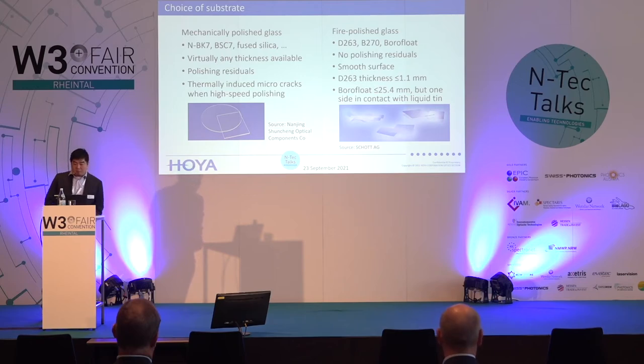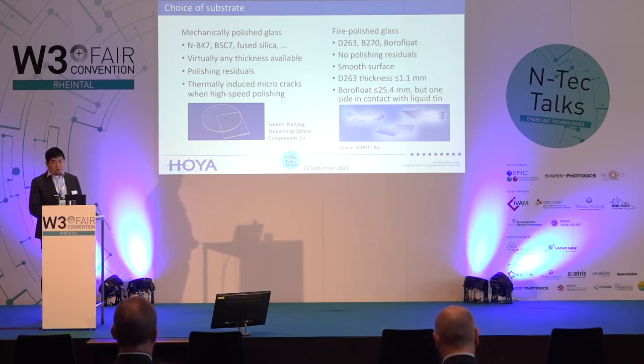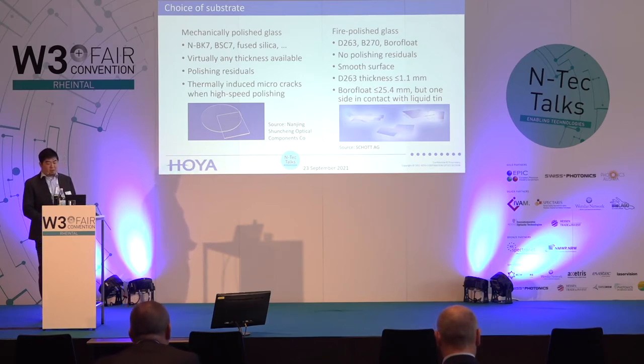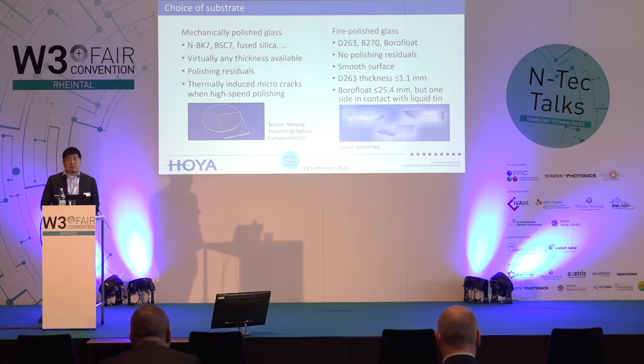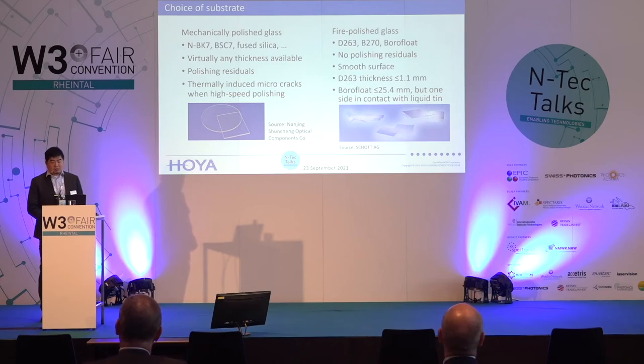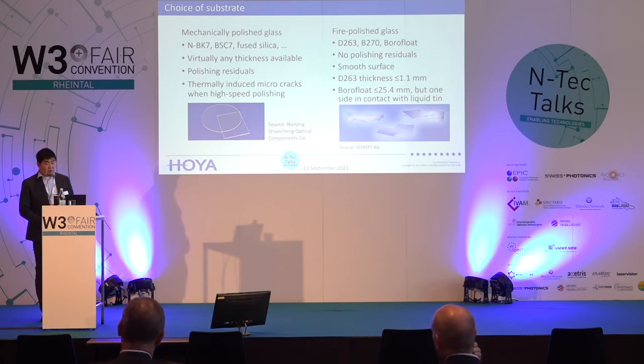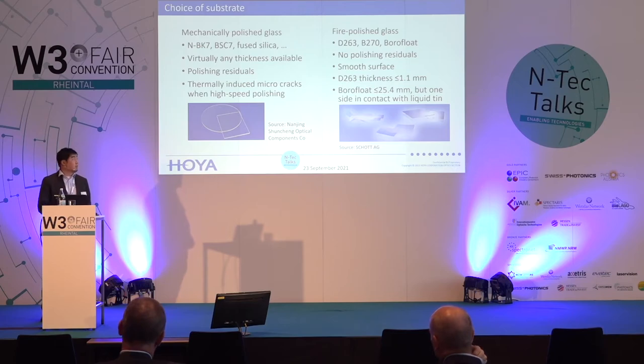People are looking for alternatives, which could be borofloat, which you can get at 1 inch maximum, but you have to consider that due to the production process as a float glass, one side of the substrate is in contact with liquid tin. And polishing might be necessary to remove this tin.